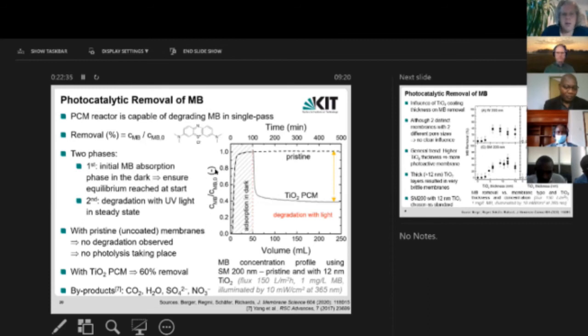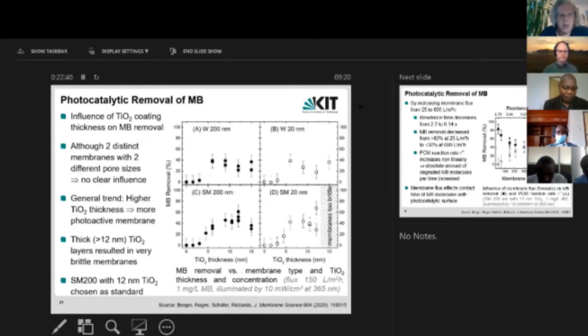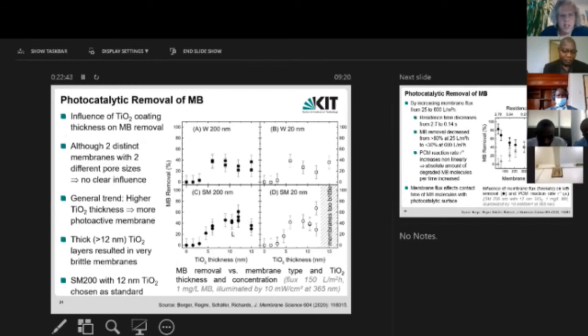Then we start to look at some other parameters. The first one we looked at was the function of thickness for the different membranes: Whatman 200 nanometers, Whatman 20 nanometers, smart membrane 200 nanometers, smart membrane 20 nanometers. And on all graphs, the y-axis is the methylene blue removal. Although there are two distinct membranes with two different pore sizes, we didn't see a strong trend in the amount of removal varying. Some performed slightly better than others, but in the end, we chose the smart membrane 200, which is the graph in C, the bottom left-hand graph, as the one to proceed with all future experiments.